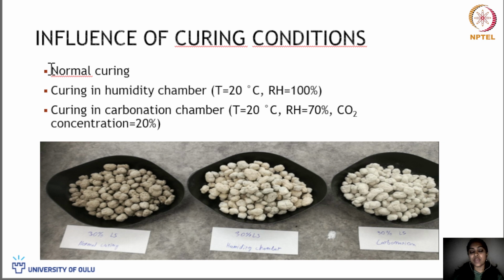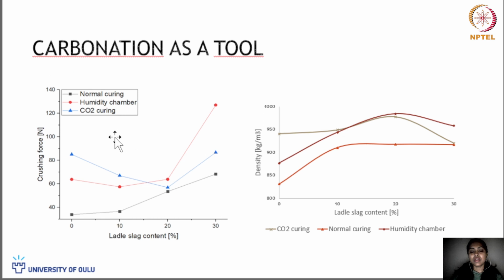Like you have seen in the video, there was normal curing, curing in the high humidity chamber, and curing in the carbonation chamber. So when you see the results of the crushing force, you see that the strength is high with the humidity chamber one when the ladle slag is increased, compared to even CO2 curing.